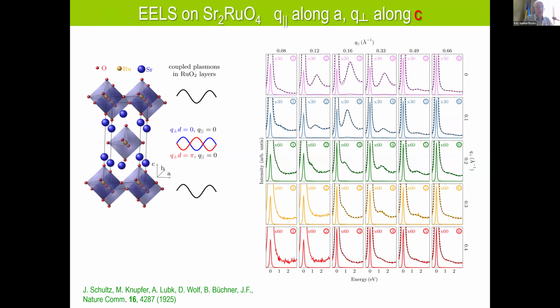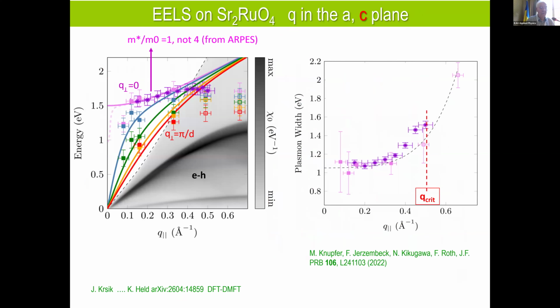So then I'm coming shortly to the ruthenates, and in ruthenates we have cut the single crystals perpendicular to the layers with ion milling. That's not quite easy. And then we can measure with the momentum transfer perpendicular to the layers. And then you see here that the plasmon, for example, with increasing Q perpendicular is reduced more and more in energy. And this is expected because we now move from the optical plasmon to the acoustic plasmons. And this is a summary of our ruthenate data. We see here the optical plasmon, and then with increasing Q perpendicular, the plasmon moves lower and lower in energy, and we see an acoustic plasmon, and this is compared with the continuum of single particle excitations.